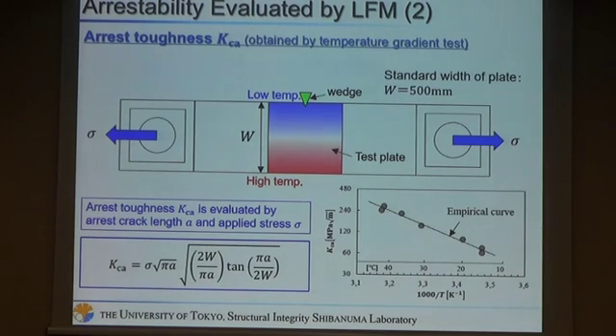This slide shows a procedure to evaluate the crack arrest toughness KCA obtained by temperature gradient test. In this test, crack is initiated at low temperature site by impact loading, and then crack propagates and is arrested at the high temperature site. Arrest toughness KCA is evaluated by arrest crack length and applied stress as this equation. And it is empirically known that the logarithm of KCA and inverse of the temperature shows a linear relationship as this figure.